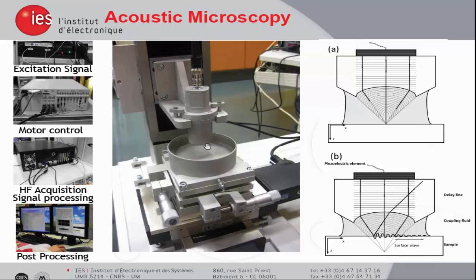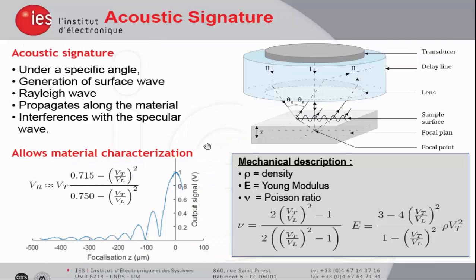Here, if you lower and if you are able to generate a surface wave, because the angular spectrum of the acoustic beams includes the Rayleigh wave angle, then you're able to generate surface waves at the surface of the sample, and this surface wave will propagate along the surface and will be received back by the piezoelectric element. And this signal reception will interfere with the specular wave. And what you obtain if you acquire the signals at different vertical positions of the sensor, then you have this kind of curve.